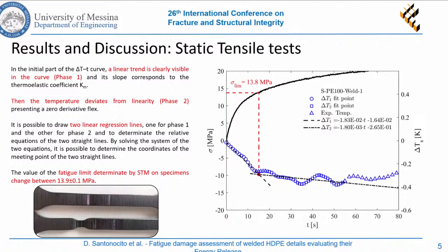As you can see, for the static tensile test, we can see a linear decrease in the temperature signal until a change in the slope, which is easy to identify. And we can make the intersection between the first phase and the second phase, assessing a stress level that can be related to the macroscopic applied stress level at which the first damage is introduced in the material. As you can see from the fracture point of view, the welded area is not affected by the failure.